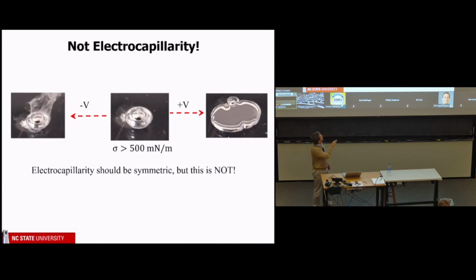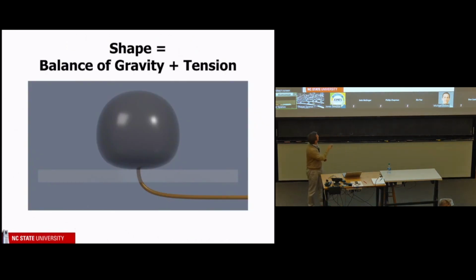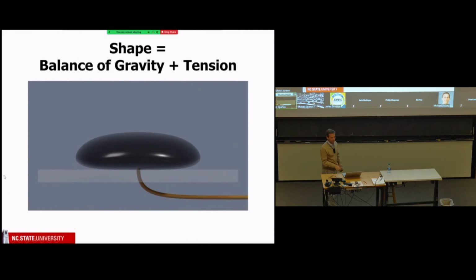In our case, when we apply a positive voltage, it spreads like a pancake, and with a negative voltage, it beads up, and in fact you can see it looks like smoke. That's hydrogen bubbles coming off the surface. So what is happening? Well, we made our own measurement with a droplet. We stuck a wire in the bottom, just enough so it wouldn't disturb the shape. We look at the shape of the drop, which represents the balance of two forces: gravity, which wants it to be flat, and surface tension, which wants it to be a sphere. As the tension lowers, it changes its cross-sectional shape, and from that we can tease out the surface tension.